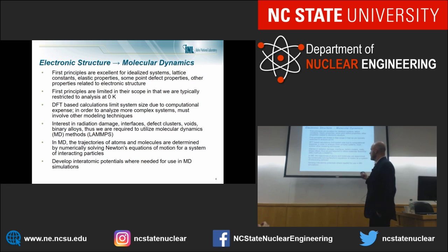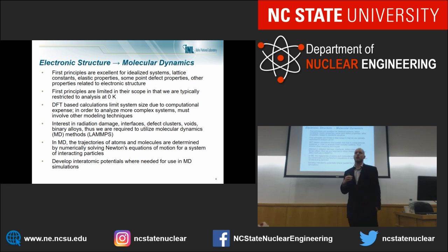So in MD, we're basically solving Newton's equations of motion. How the particle interactions are determined is by an interatomic potential determining the energy of the system as a function of r, so as a function of the distance between the atoms that are interacting. And you can have many-body interatomic potentials as well that can have angular components to the system, where you can have complex bonding where all these interactions are described.